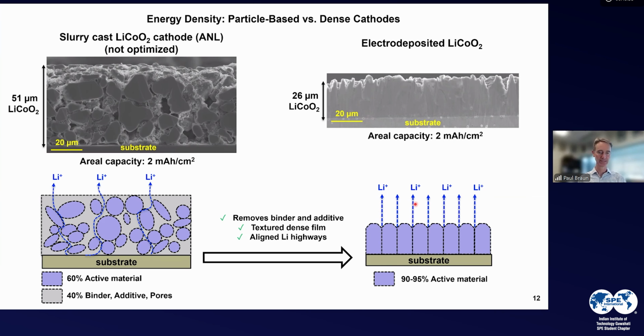In addition, the tortuosity is much diminished. Here, the lithium transport is all in the fast direction. Here, the lithium transport is very complex, it has to go around all of the particles. And what this does is it gives a much diminished rate performance relative to the highly textured material.